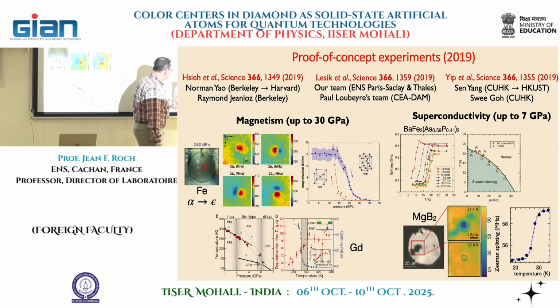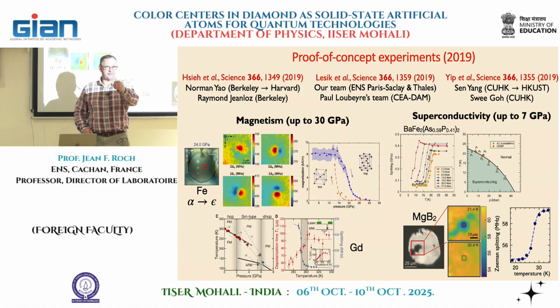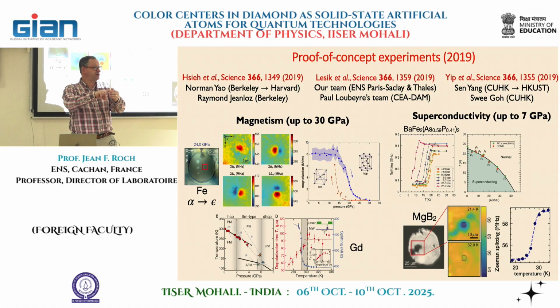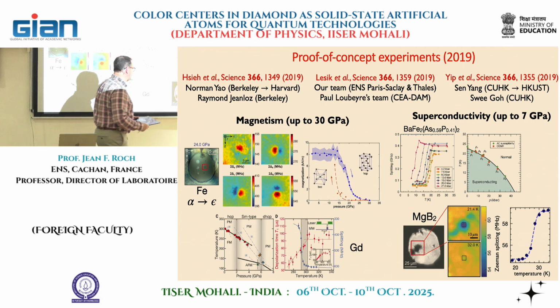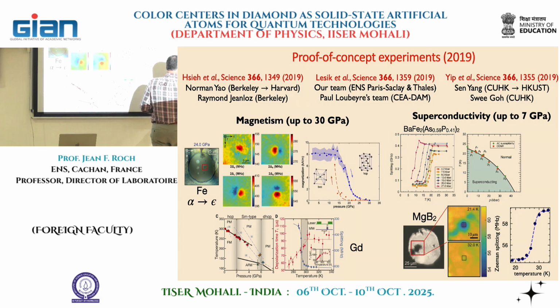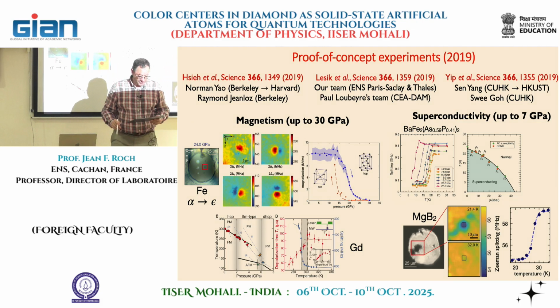And what we see is, below the critical temperature, we apply a magnetic field like that. And the magnetic field in the z direction will have the same projection on the 4 axes of all 4 families that I have. This is important. So all 4 families will have the same Zeeman splitting. And now I plot the Zeeman splitting here as a function of the position. And this map is directly obtained by wide field magnetometry.